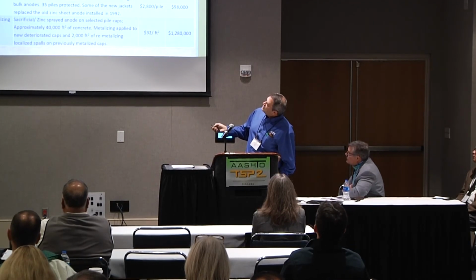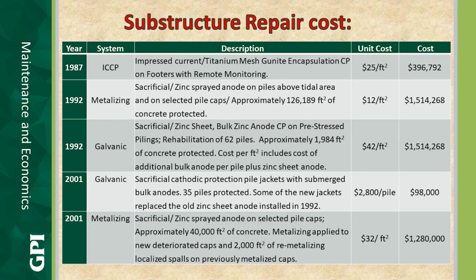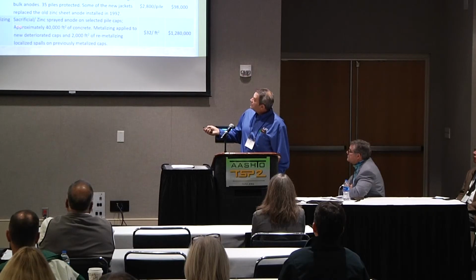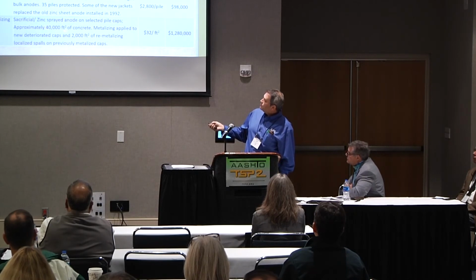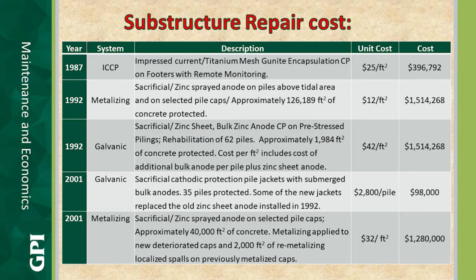We've got 1992, we installed galvanic cathodic protection, sacrificial zinc, bulk zinc anodes, as we showed in the pile jacket schematic, and rehabbed approximately 62 piles. About 2,000 square feet of concrete was protected, and the cost per square foot includes the cost of additional bulk anodes per pile plus the zinc sheet anode, about $42 a square foot for a sum of about $1.5 million. Some metallizing in 2001, about 40,000 square feet of metallizing at about $32, a $1.3 million investment.